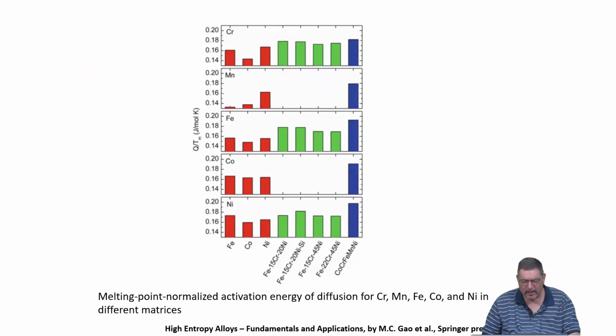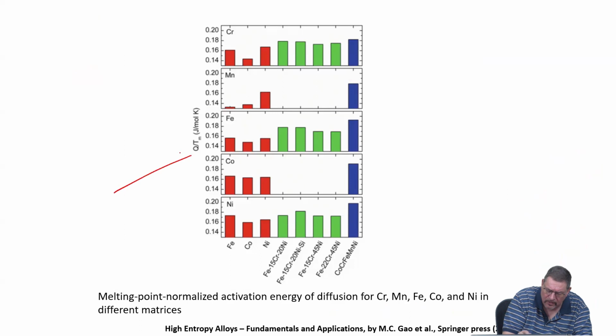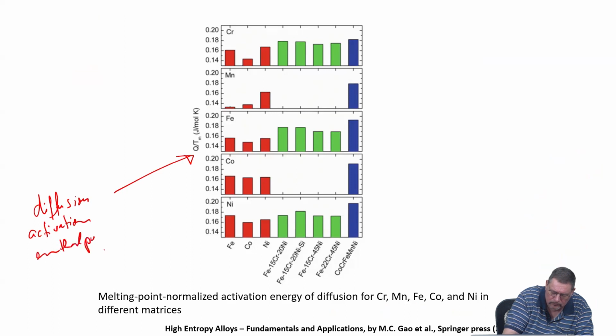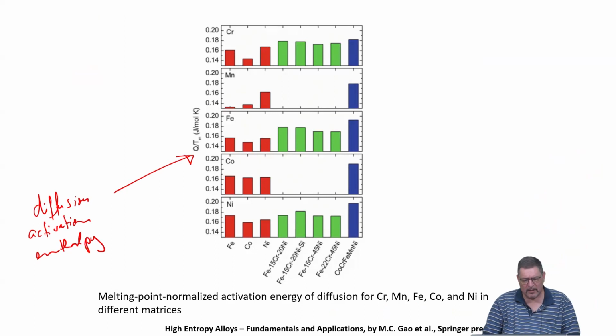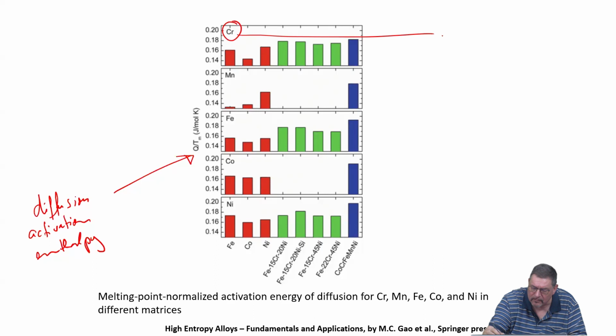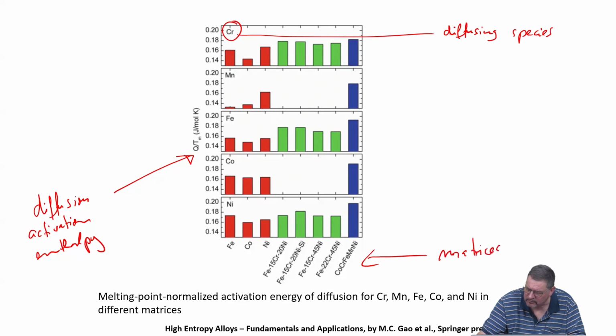They also have shown here a plot, which is the diffusion activation enthalpy, which they name Q. And it's normalized by the melting temperature. And it's plotted for the diffusion of these elements in the different matrices, right? So this is again the diffusing element. And these are the matrices. Again, the question the experiments answer is, how large is the diffusion activation enthalpy, let's say, of chromium in pure iron, of chromium in pure nickel, and so on.